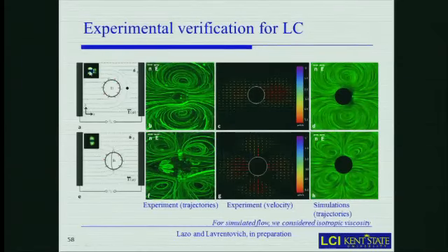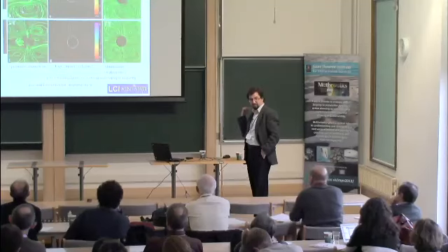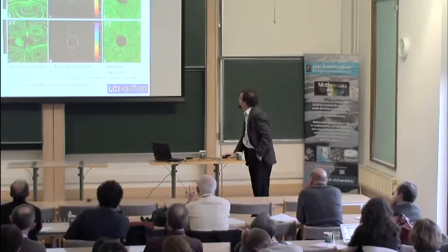Okay, this is just the mechanism, but here is the experimental proof that whenever you apply an electric field to the sphere in the liquid crystal with this dipolar configuration, the motion of ions really occurs, and it is not compensated. Here you see the trajectories of ions around the particles; they do not have symmetry with respect to the vertical plane, and this is what forces the particle to move.